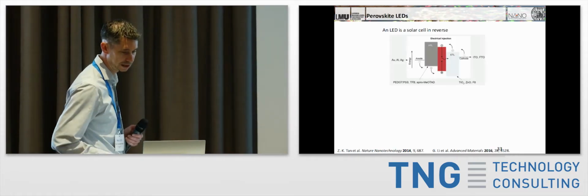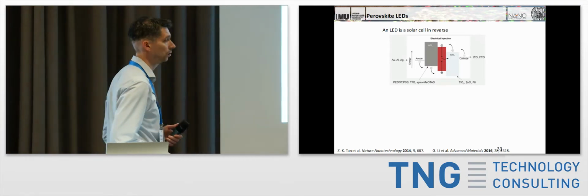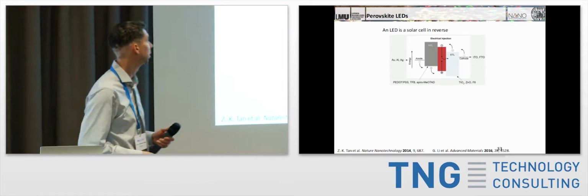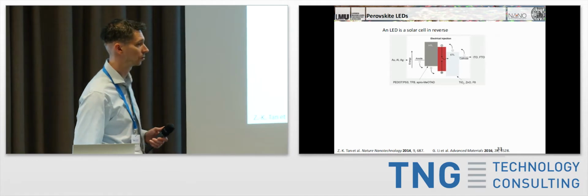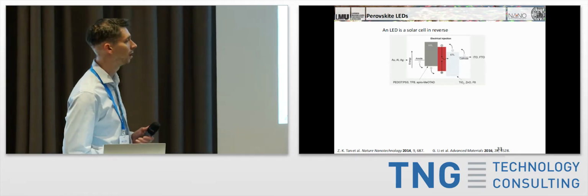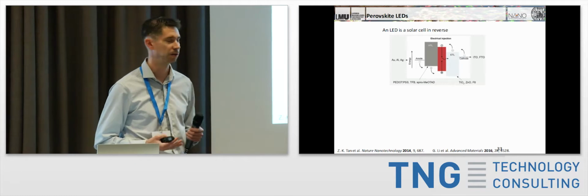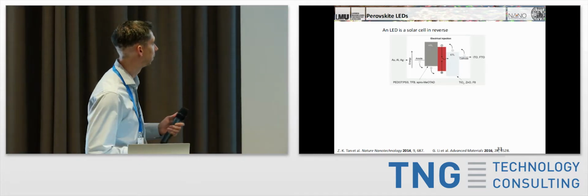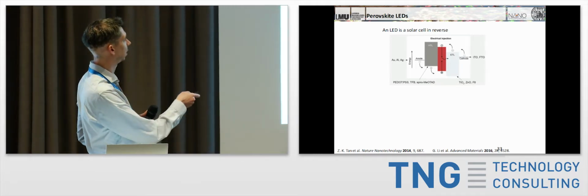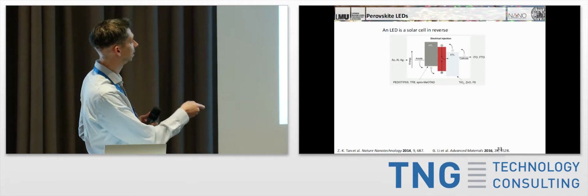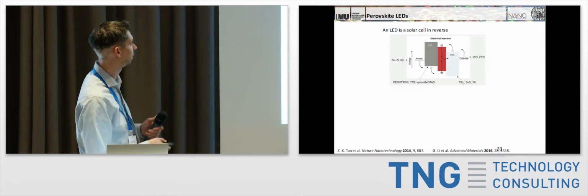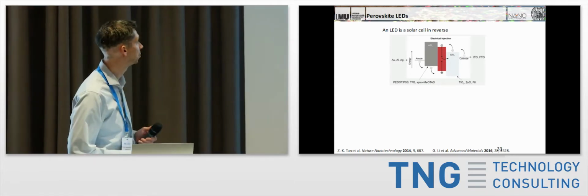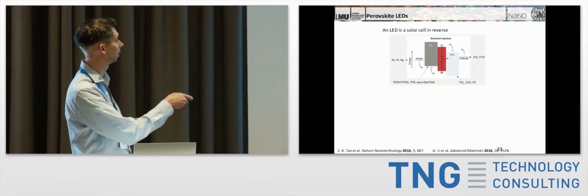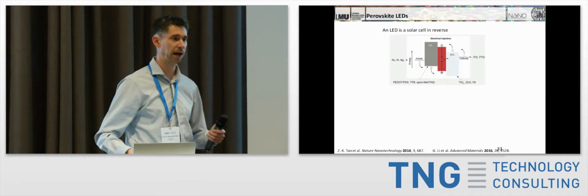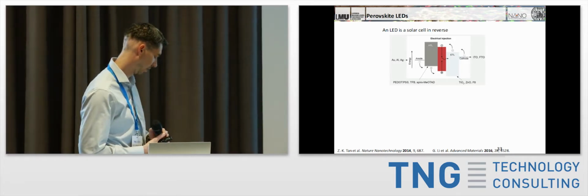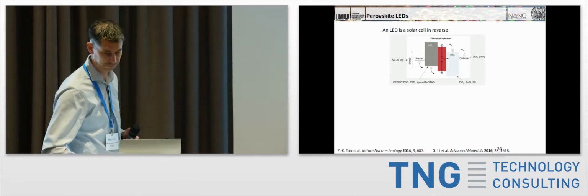Okay, what is an LED? An LED is essentially just a solar cell that you drive in reverse. So technically, you can use a solar cell and put the voltage on the wrong way around, and you actually get light out of that. You won't be able to see anything, obviously, because it's silicon, and so it emits in the infrared. But it's essentially the same principle. It's just that now you're taking electrons and holes and injecting them, so you're going the wrong way around because you have a current. They are able to overcome these energies, and then they reach the middle of the perovskite layer, in this case, and recombine. The electron falls down into the valence band, and produces a photon.